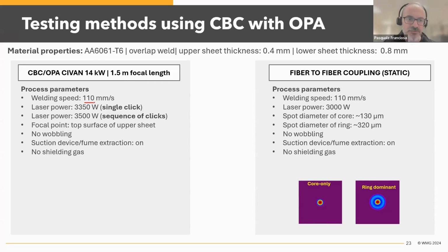So welding speed was constant for all the experiments. We use 110 millimeters per second across all the experiments. Power was, you can see, on average between 3.3 and 3.5 kilowatts for either a single click or a sequence of clicks. A click is understood as a diffraction pattern, so one click is associated with a single diffraction pattern. No wobbling, no shielding gas, and the fumes were extracted with a fume extractor positioned nearby the weld area.